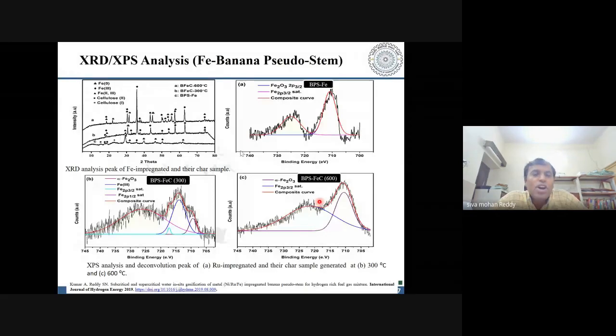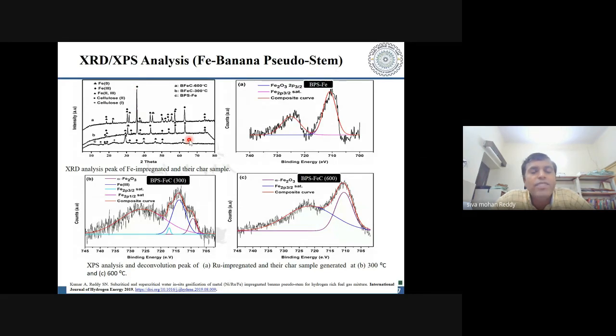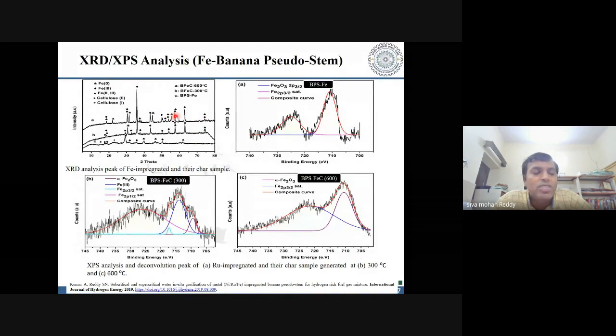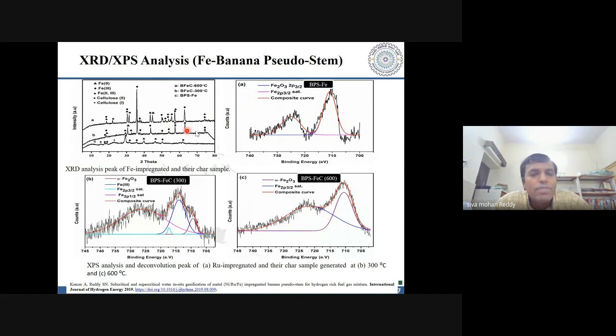Here we have an interesting phenomenon. As I've already mentioned, the XRD profile, or the XRD spectra, for the char that has been obtained at 300 degrees centigrade and at 600 degrees centigrade. So you see that iron existed mostly in its oxide form. You have very sharp, intense peaks around 74 degrees. And you have one more sharp, intense peak, which is coming around 46 degrees. So you say that alpha actual metal of iron is there with the 100 Miller indices plane, and you have oxide, that is, iron mostly existed in the +3 form.